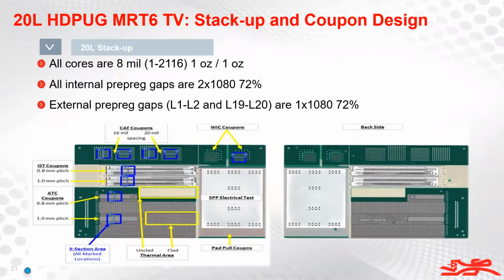It also has excellent CAF performance. This has 16 mil and 20 mil spacings on it, but this material passed that testing with ease. It also thermally, because it's halogen free and its resin system basis is a very high temperature capability. All of the coupons that are on this board pass relatively easily for this type of testing. And so one of the things that we're currently working on is developing test vehicles that look at the Z-axis gap. And so there's ongoing work for capability, but this is our standard capability board here that we use for evaluating materials.